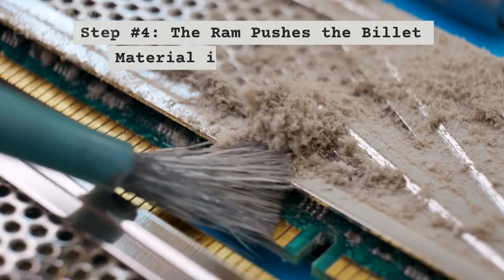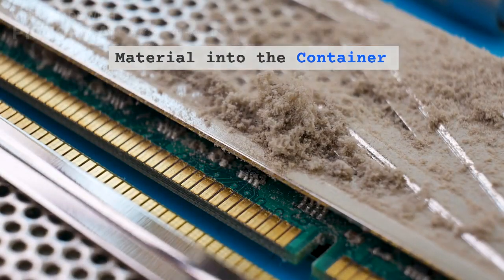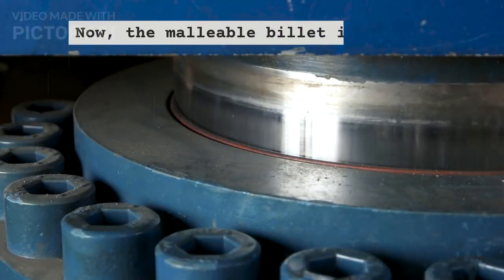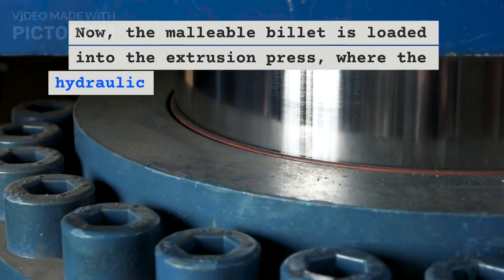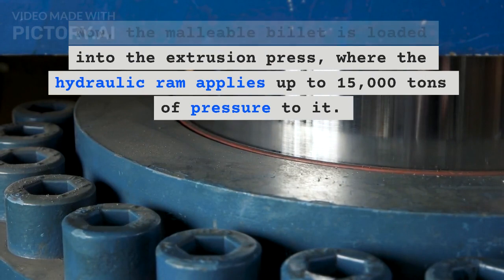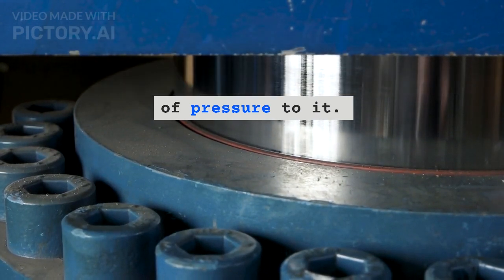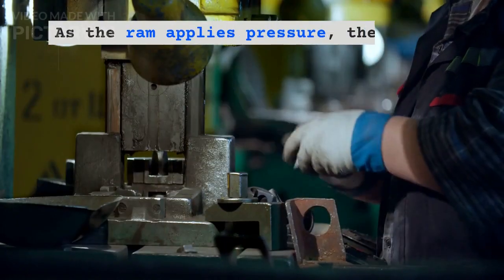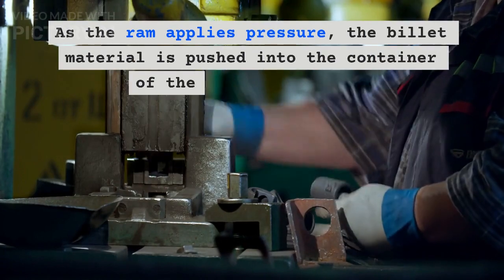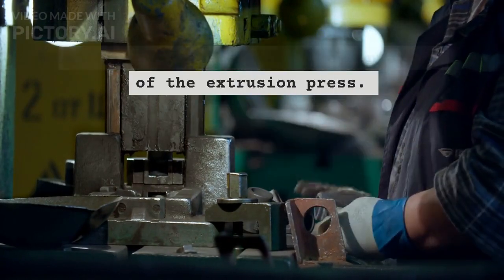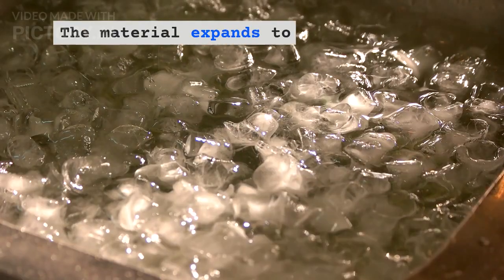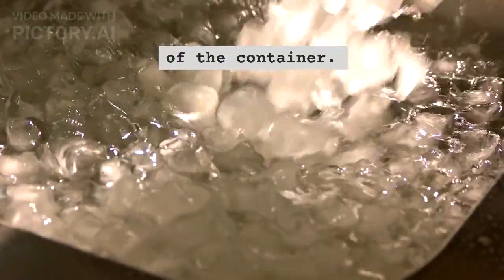Step 4. The ram pushes the billet material into the container. Now, the malleable billet is loaded into the extrusion press, where the hydraulic ram applies up to 15,000 tons of pressure to it. As the ram applies pressure, the billet material is pushed into the container of the extrusion press. The material expands to fill the walls of the container.